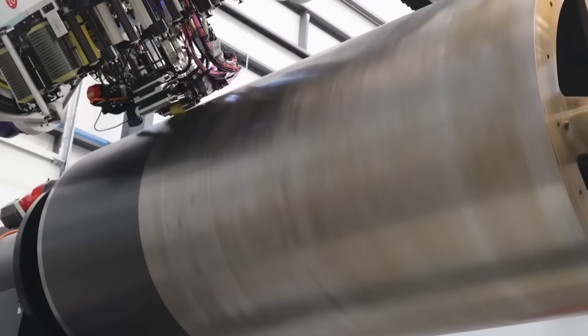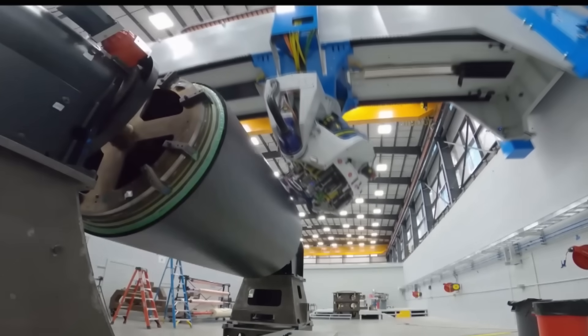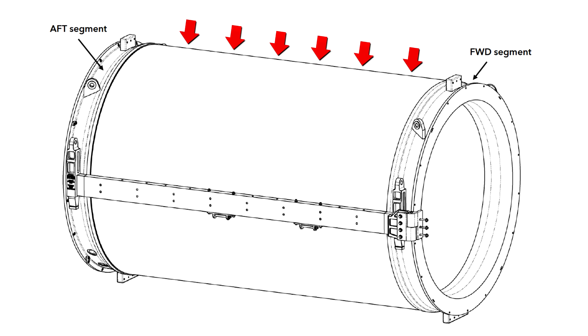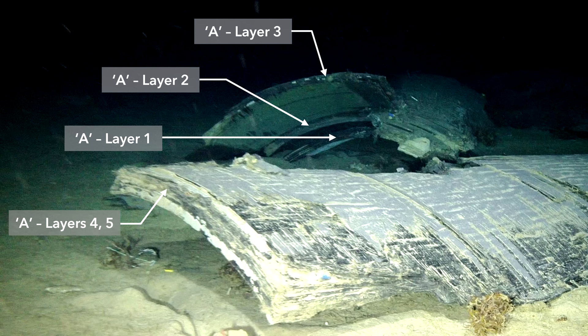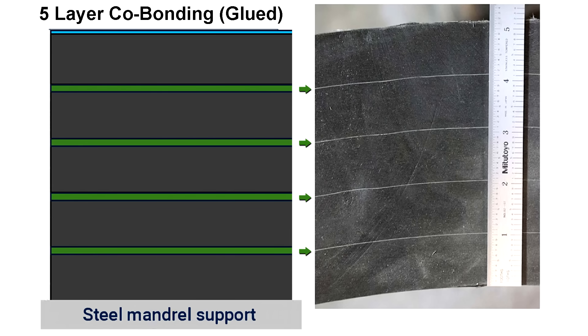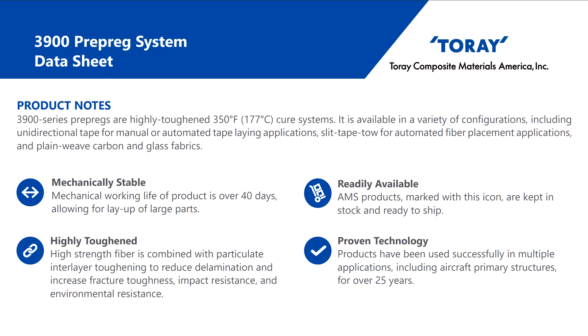Now we are ready to talk about the two things that could have made the hull weak right from the time of fabrication, and perhaps weaker after multiple dives. The issue is the potential for increased inward deflection, because that is what will link to the NTSB wreckage findings. Number one: it starts with the fact that the layup, the curing, and the debulking did not achieve the Toray specifications for porosity. The specs for the system, if cured properly, had an expected mean void volume of 0.461%. Let's see what Dr. Kramer said about that.